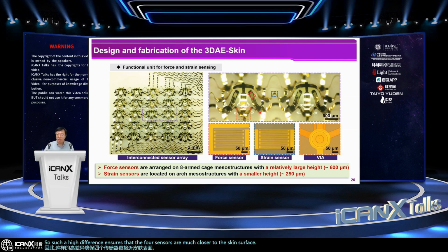And additionally, the distance between the center of the cage mesostructure to the adjacent one is 2.5 millimeters. So the entire e-skin device with an array of 5 by 5 has a comparable dimension to the size of the fingertip. And over this area of fingertip, we have 200 force sensors and 40 strain sensors in total.